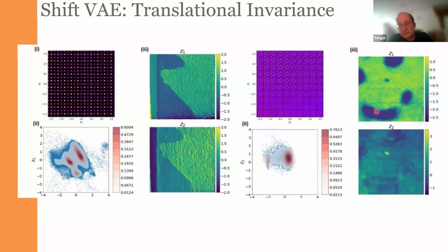So in this case, it's even simpler. We have a very simple latent distribution that has 2 peaks. One peak corresponds to one phase, another peak corresponds to another phase. And our second latent variable actually shows us something else. We don't know what this contrast is, but simply by the fact that this contrast appears on length scales much larger than atomic scale, we know that it's something real. It represents some physical factor of variation inside the system.